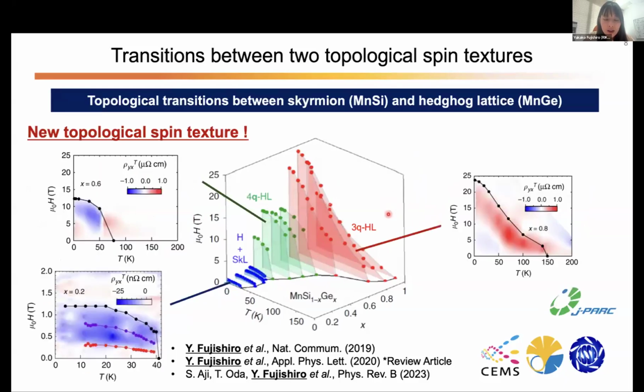And then we also did a transport measurement to identify the topology of the spin texture, as I just presented before. So in the conventional skyrmion lattice, we have a negative topological Hall effect, as shown in this phase diagram. And in the conventional hedgehog lattice state, we have a sign change from negative to positive towards the phase boundary state, which is also confirmed in pure manganese germanium.